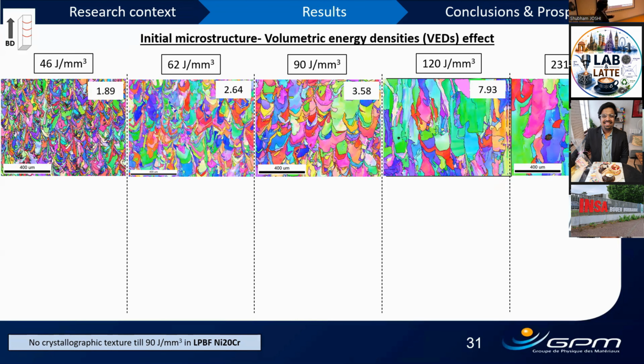So volumetric energy density is connected to laser power. I do not have a formula here, but it is normally connected to laser power, hatch spacing, powder thickness, and the laser speed. Depending upon that, we can calculate the process parameter, the volumetric energy density, which for time purposes I will just call VED, because it takes a long time to say. So we consider a long range of VEDs, and what we see here from 62 joules per millimeter cube was our sample that we have been studying until now.